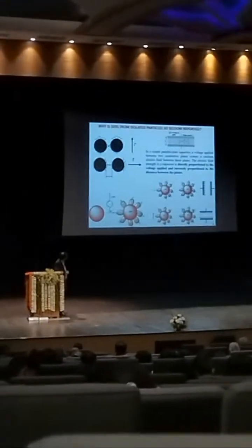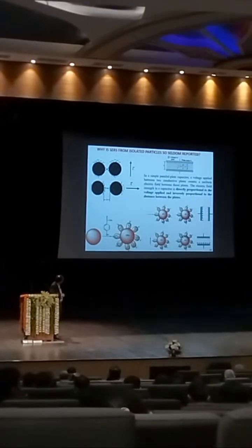But think about when we apply the electromagnetic field in this direction or even this direction, it gives a capacitor here, like positive and negative. Similarly, for the negatively charged ligands, this side it will give positive and negative. So this capacitor enhances the field so highly that we can reach an electromagnetic enhancement of 10 to the 11 to 10 to the 12.